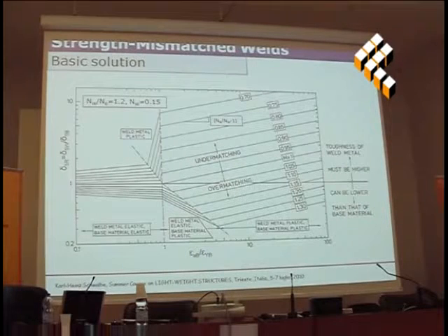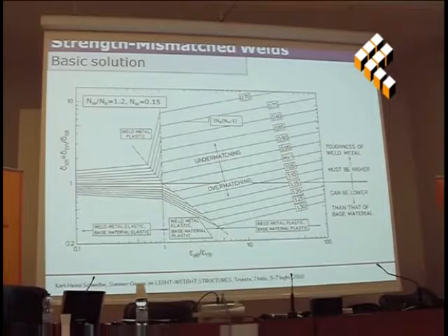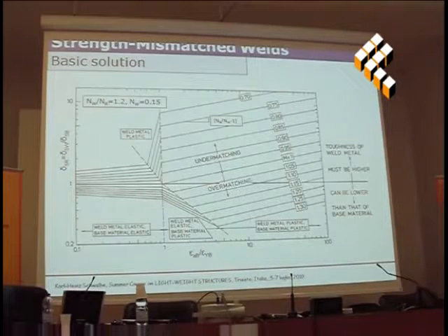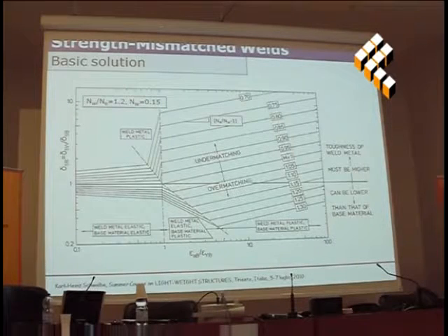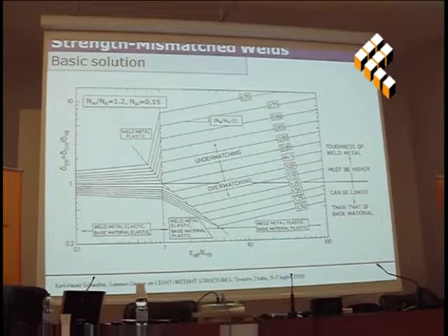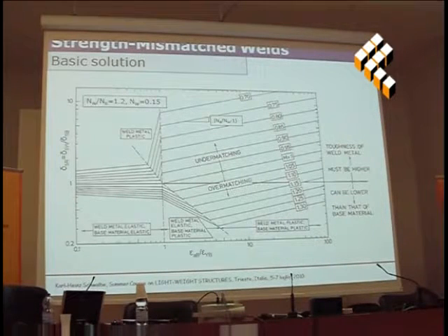Think of the right-hand side of the equation, toughness. When you vary toughness by microstructural manipulations or thermomechanical treatment, you are happy when you achieve a 50% increase in toughness, which is a lot, as compared to an order of magnitude increase in the driving force.